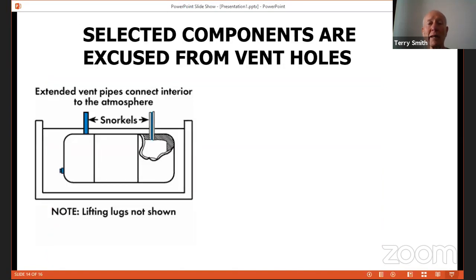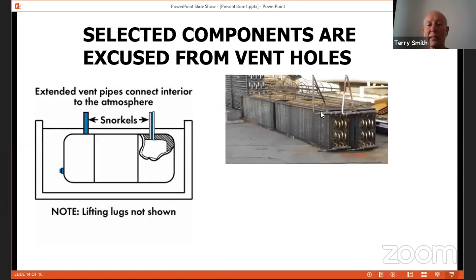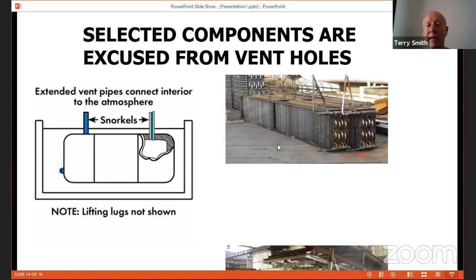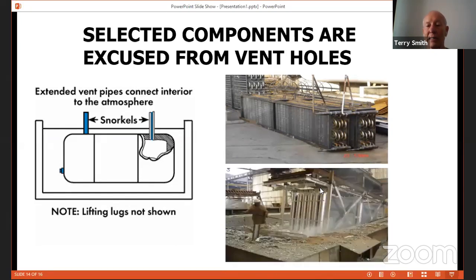Selected components are excused from vent holes. Here we have an item like this, galvanized on the outside, with snorkels that allow the item to be immersed, much the same as the heat exchangers. You can see the snorkels sticking out. When it's put into the galvanizing bath, it is forced in, so it actually displaces the zinc and coats only on the outside, and then they cut the snorkels off afterwards.